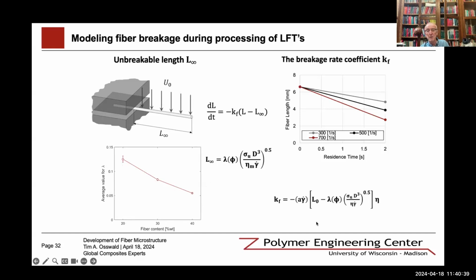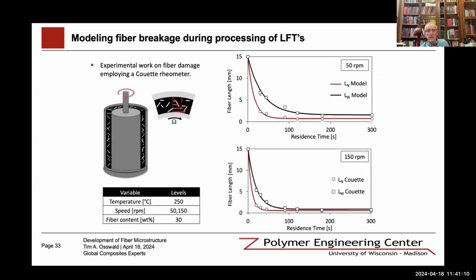And K sub f is a similar effect. So we have the breakage rate for different rates of deformation, and we can then attribute that obviously to the infinite length and to the length of the original fibers, the initial fiber length. And so if we compare the model then with a simple shear flow using our Couette device and experimentally measuring the length distribution during the process, we can see how the model and the experiments actually match quite well.